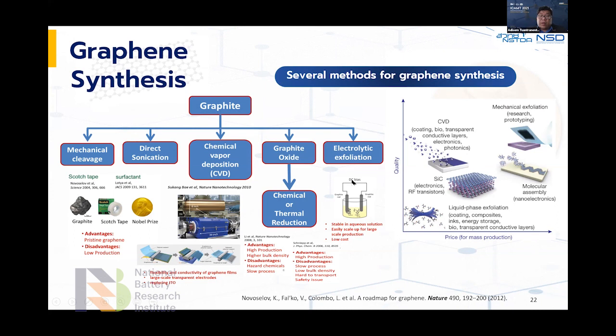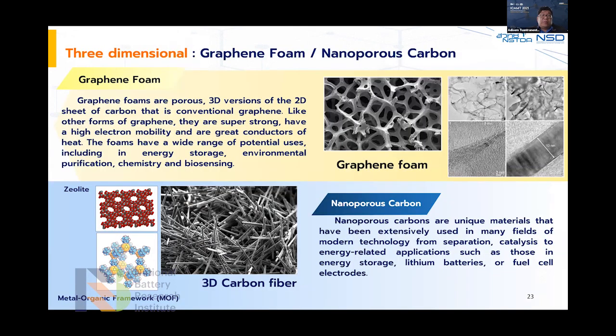So there is still room for research on the mass production of high-quality graphene. Also, graphene is two-dimensional, but we can construct three-dimensional structures of graphene using various techniques. One of them we call graphene foam. For graphene foam, we use a template, like a nickel template or copper template, and then we grow the graphene using CVD on the surface of the template, and then we etch. We can have pure graphene in a 3D structural form.